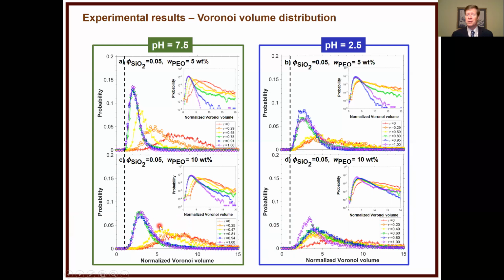Now, something we discovered that was a little bit unique to these systems, and I haven't found really in the analysis, there are many other papers that analyze microstructure this way, but it looks like there's a self-similar thing happening here. There are some articles long ago talking about how they should have a log normal distribution. And that's why we plot a log linear profile, because you can, number one, see these tails better way out to the distribution. Then you can see the difference in those tails.